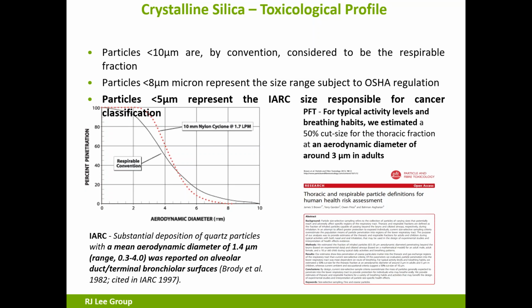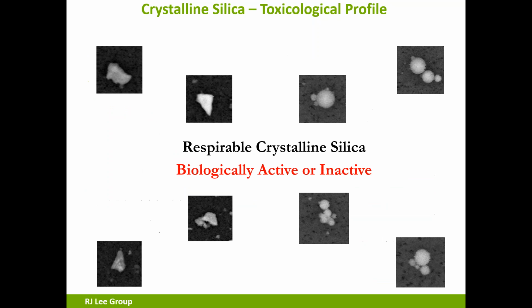The IARC has a mean aerodynamic diameter of 1.4 microns with a range of 0.3 to 4, which is the basis for the carcinogenicity. And a more recent article from Particle and Fiber Toxicology identifies an aerodynamic diameter of around 3 microns in adults. So the bottom line here is, even though by convention we use 10 microns, that is not the bioavailable crystalline silica. The bioavailable portion is less than 5 microns. Anything above 5 is irrelevant. It cannot reach your lower alveola and cause problems.